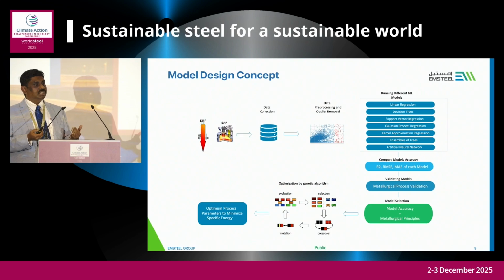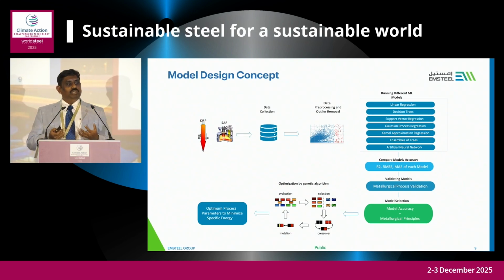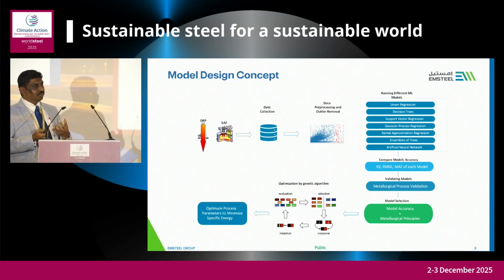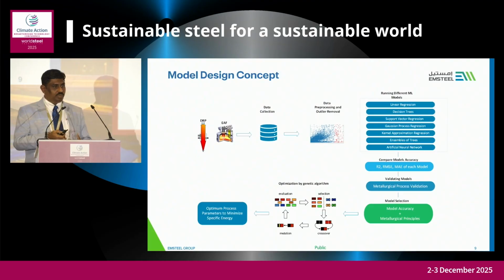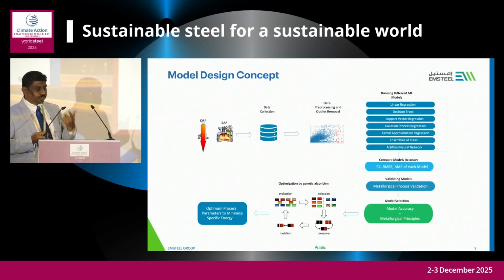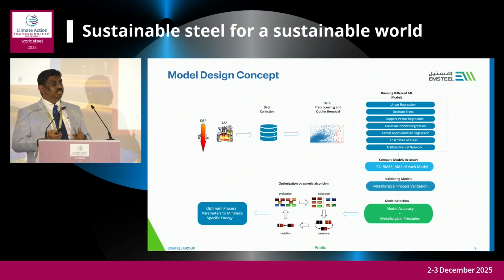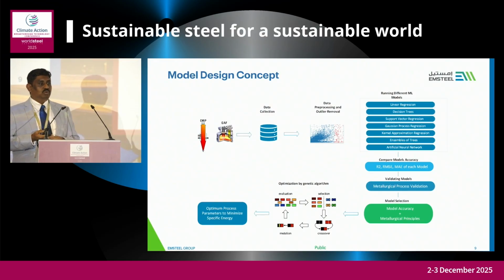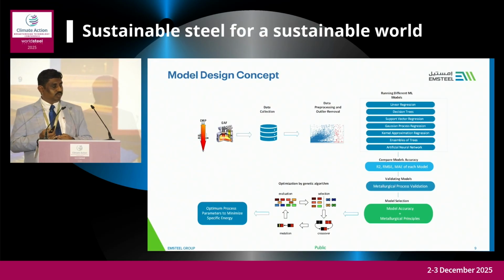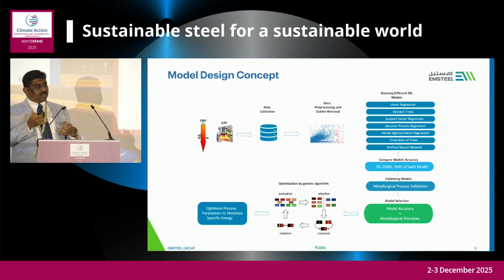So we are not considering that as the right model. We are combining the machine learning model performance with the metallurgical variations, and then consider that the best model. After developing this model, we put it into an optimization algorithm called GA, genetic algorithm, to optimize the process to minimize the energy.